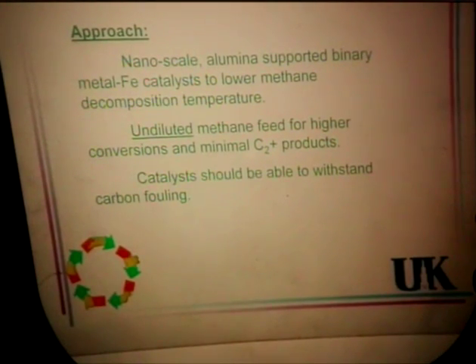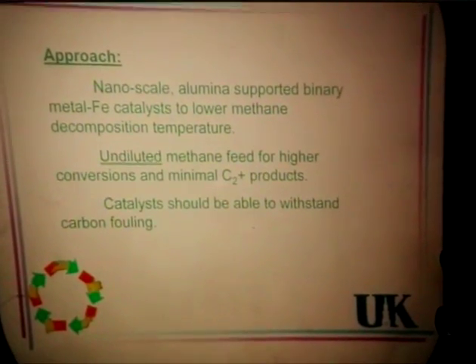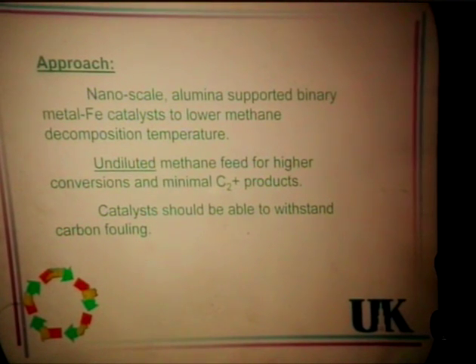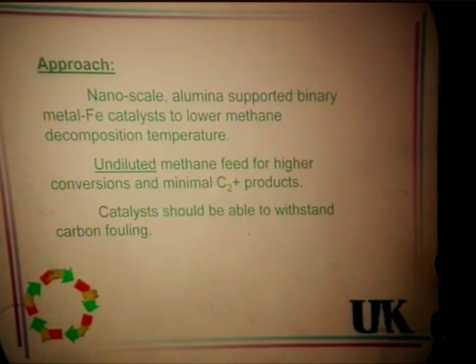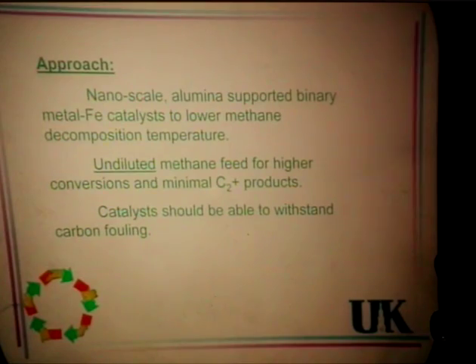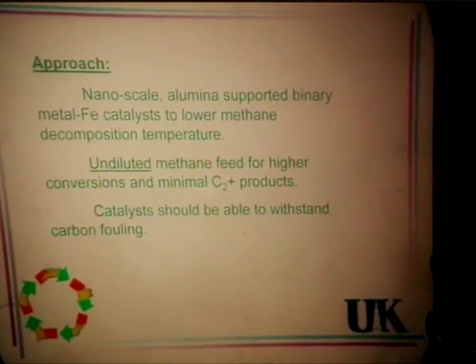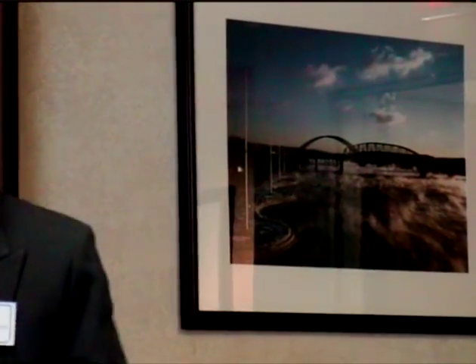Our approach is to use nanoscale alumina supported mono and binary metal catalysts to decompose methane at lower temperatures. Methane is a very inert molecule. To decompose it, it needs higher energy. We are trying to lower the methane decomposition temperature. Here we have used undiluted methane as a feed, and the catalyst should be able to withstand the carbon fouling we are expecting.